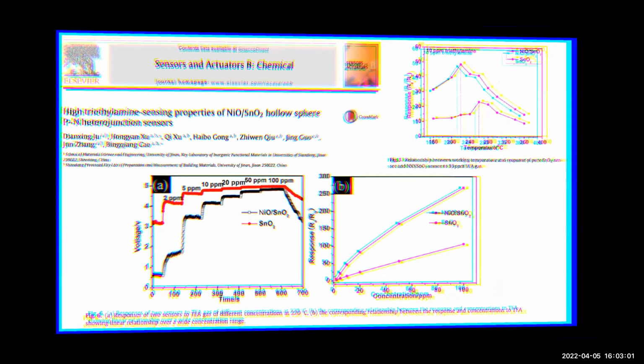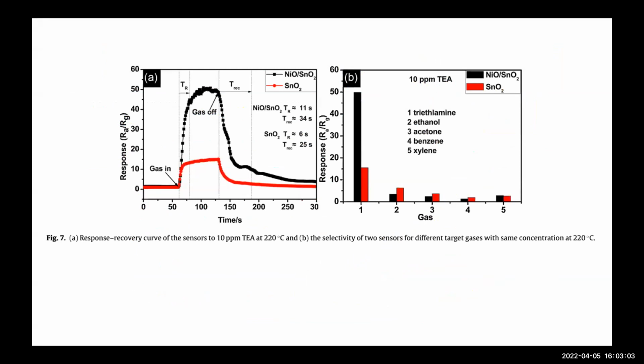Now in the next, you can see the graphs. Both sensors can quickly respond to triethylamine gas. Here you can see for the composite NiO/SnO2 and the pure SnO2, the response times are 11 seconds and 6 seconds, and the recovery times are 34 seconds and 25 seconds. So you can see the composite sensor needs more time to recover than the pure SnO2 sensor after the gas is removed.